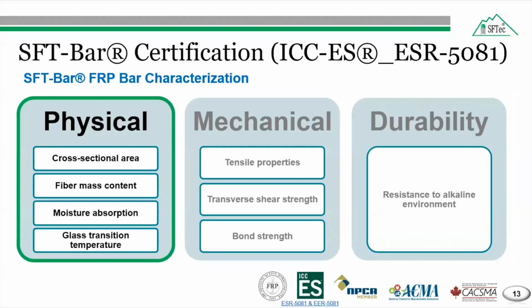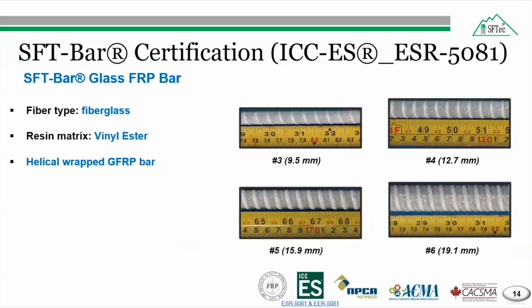So starting with the physical properties, four different kinds of physical properties are required for the certification. Those are cross-sectional area, fiber mass content, moisture absorption, and the glass transition temperature. So the glass fiber reinforced polymer bars used in the current certification were produced according to the pultrusion process and were made of continuous glass fiber embedded in vinyl ester resin matrix. So all the GFRP bars in the study had a helical wrap surface to increase the bond between the bar and the concrete. Four different types of GFRP bar were investigated: number 3, number 4, number 5, and number 6, which have a nominal diameter ranging from 9.5 millimeters to 19.1 millimeters.